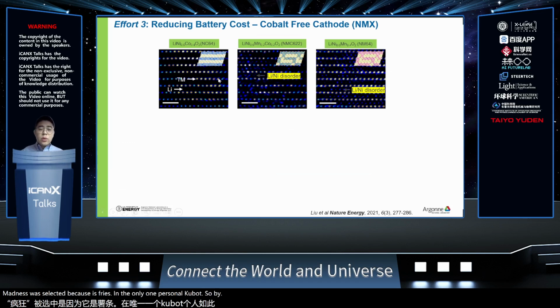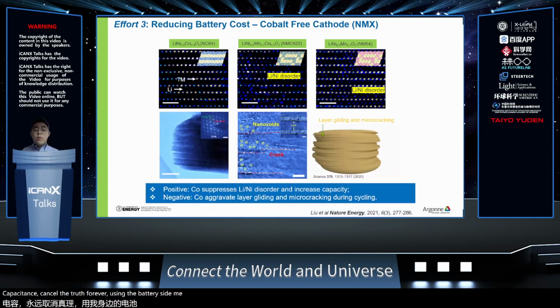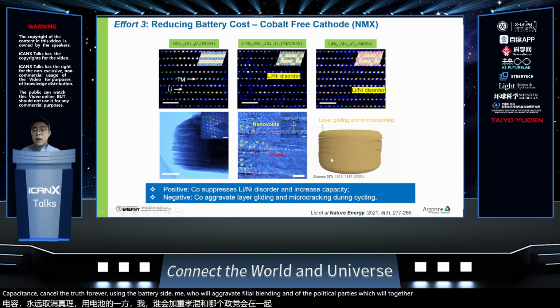By characterizing these materials, we found cobalt can suppress the lithium-nickel disorder. The lithium-nickel disorder is a common structural defect that reduces the capacity. As a result, cobalt can increase the capacity of cathode materials. However, during battery cycling, cobalt will aggravate the layer gliding and the particle cracking, which together accelerate the capacity fading. So clearly, cobalt is a double-edged sword for batteries.